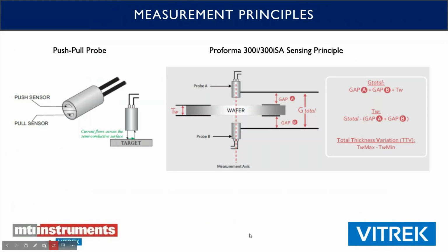other. We use one on the top of the machine, or on the top of the wafer, and one on the bottom. And you can see the math on the right is how we calculate both the thickness and the shape of the wafer as it moves between the two probes. So you can get thickness variation. There's a host of different measurements that you can do, but this is the technology used for that.